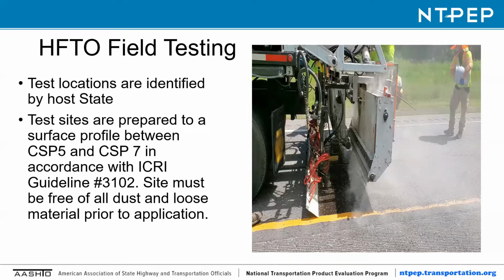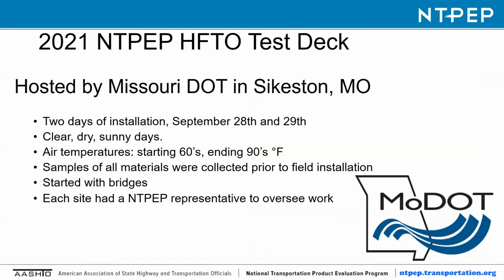But what we do with the HFTO field testing is all the concrete, whether it's a bridge deck or concrete pavement, is shot blasted to a certain degree, CSP 5 and CSP 7 in between there, with the International Concrete Repair Institute Guideline 3102. Site must be free of all dust and loose material prior to application. The Missouri DOT and NTPEP got a company out there to shot blast these areas to have them ready to go when we do apply to the concrete. The asphalt, of course, is all just air washed like we do every day in a regular contract.